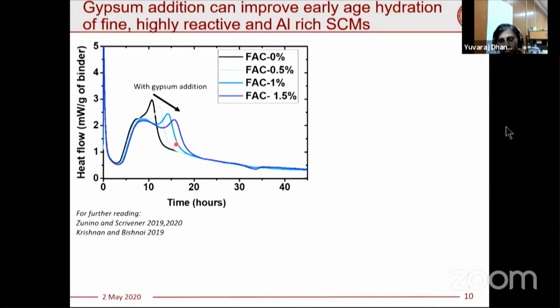So in these cases, what we have to do is start increasing the dosage of gypsum. You can see the typical curve for the class C fly ash, and when you start increasing gypsum dosage, you can push this aluminate reaction. By doing so, you can see the width of the silicate reaction is being increased, which means we are allowing the C3S reaction to happen properly.